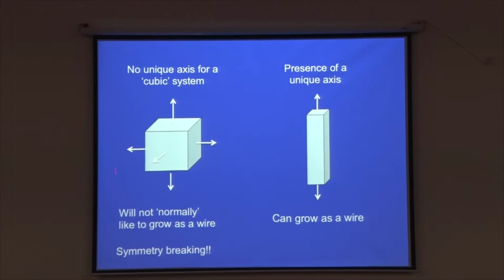So, when we have a cubic crystal, in which the building block is something like this, there is no unique direction along which the crystal will like to grow, and therefore, there is no reason that this cubic crystal will grow as a wire. Whereas on the other hand, when you have an orthorhombic crystal, or even a tetragonal or hexagonal crystal, there is a unique direction along which the crystal can grow faster, for example, and end up as a wire. So, how do we actually end up with a wire with a cubic structure?